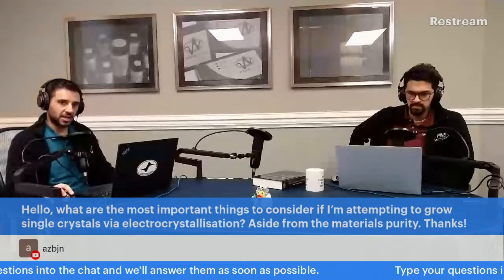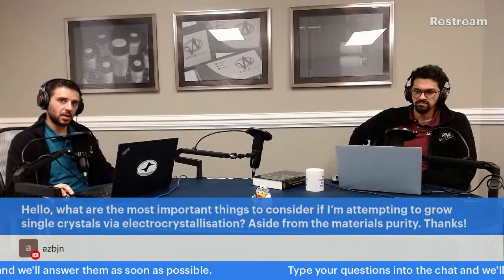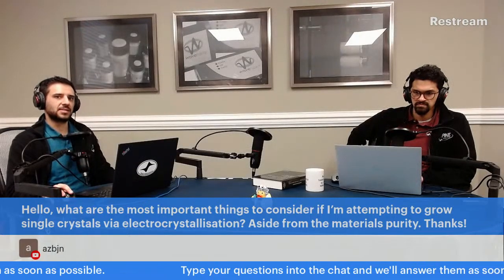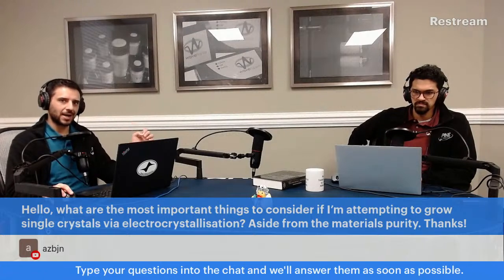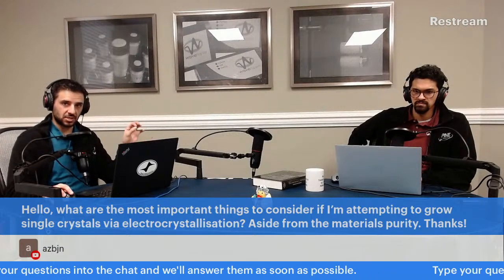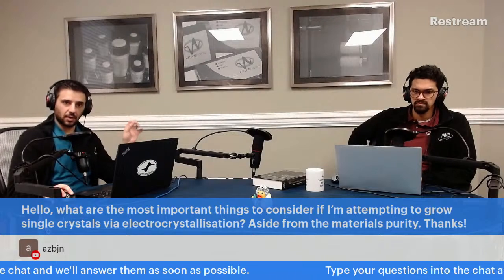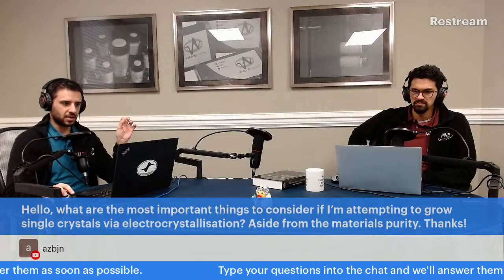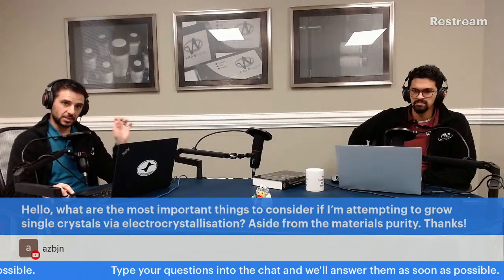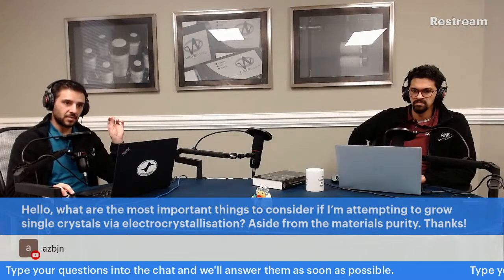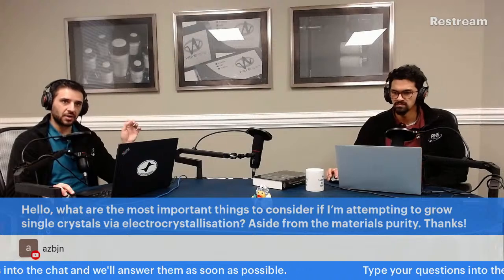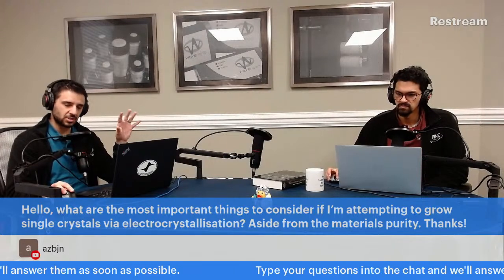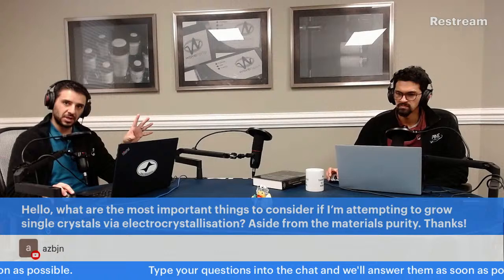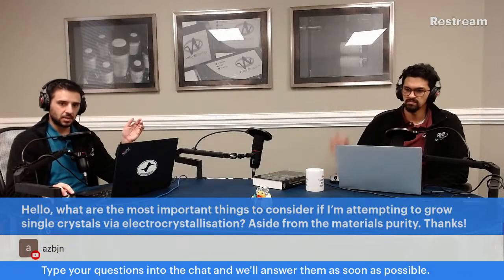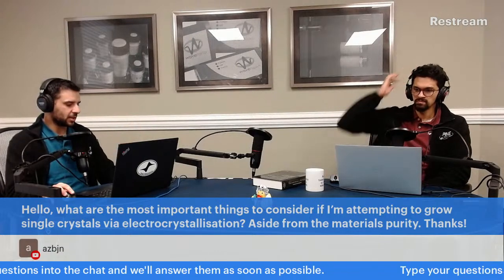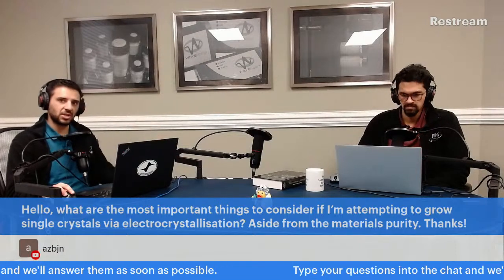There's a lot here, right? You have to determine procedurally: is this the kind of thing that requires a constant rate, which would be current, right? And you're trying to grow a single crystal, so that's usually one specific crystal face. If you have too high a current, too much passivation layer, too much other stuff, you might convolute it. It might cause a polycrystalline formation, and that would be bad.